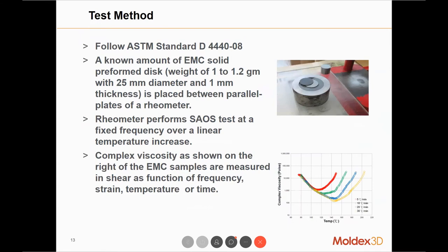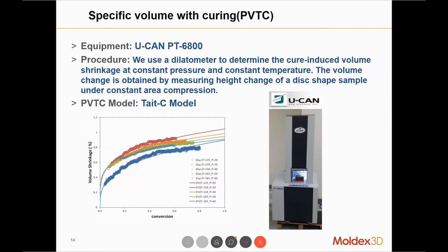So what it looks like is we'll use a known amount of EMC solid disk at a certain diameter. We'll place it in between two parallel plates of a rheometer, and we'll fix the angular speed of the disk under a linear temperature increase so that the heating rate remains the same, and we will record the strain and the temperature versus time, and then we'll get the four different viscosity curves, as you can see from here. So four different curves from four different heating rates, and with that we'll be able to build the whole viscosity model. Okay, so those are the important properties for the filling stage.